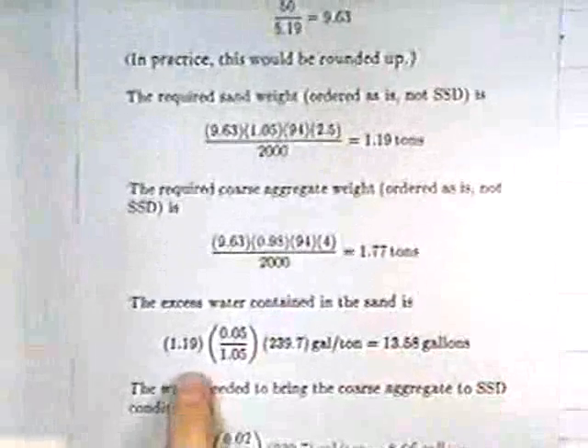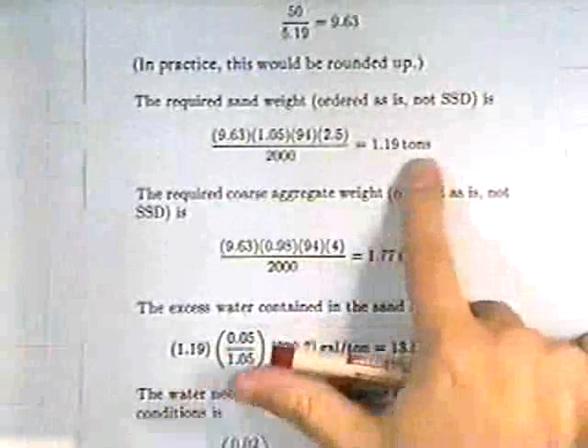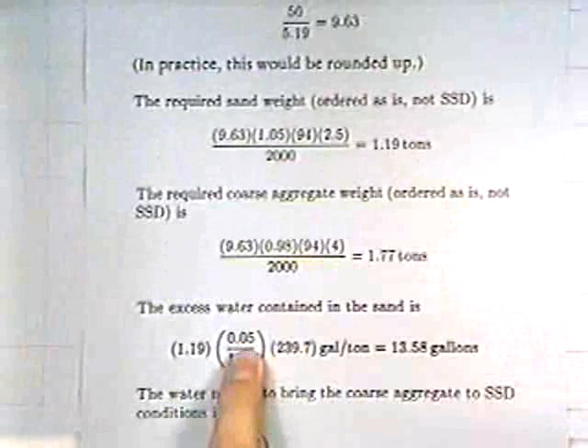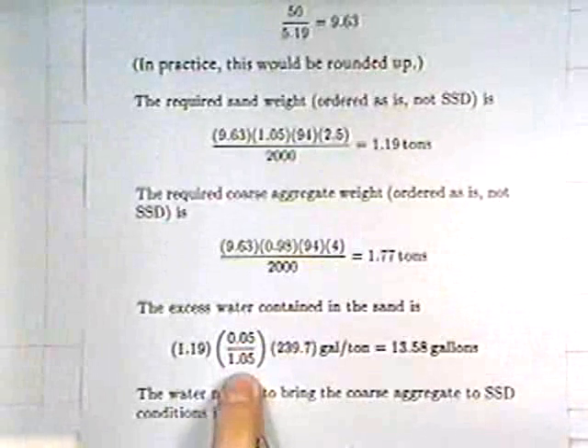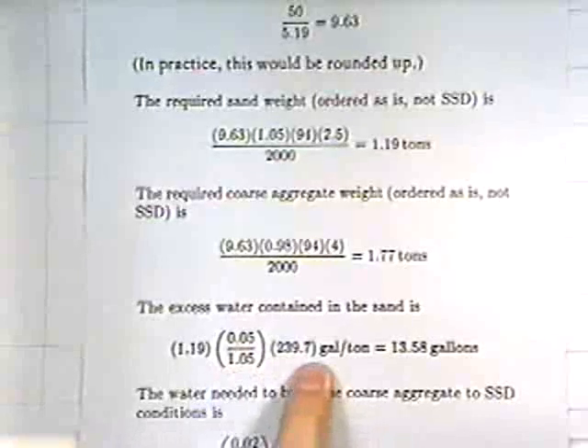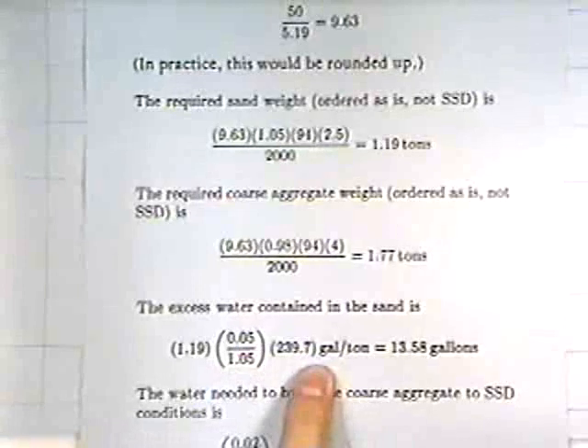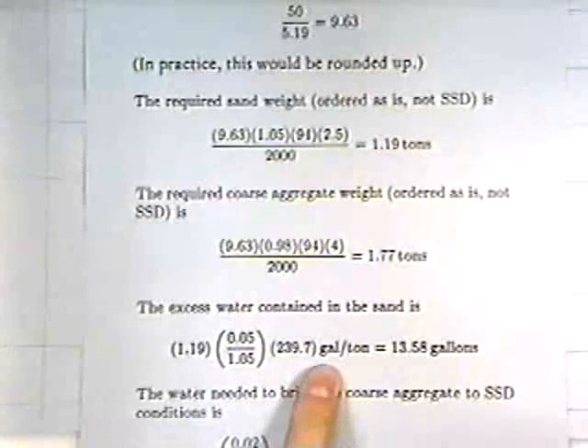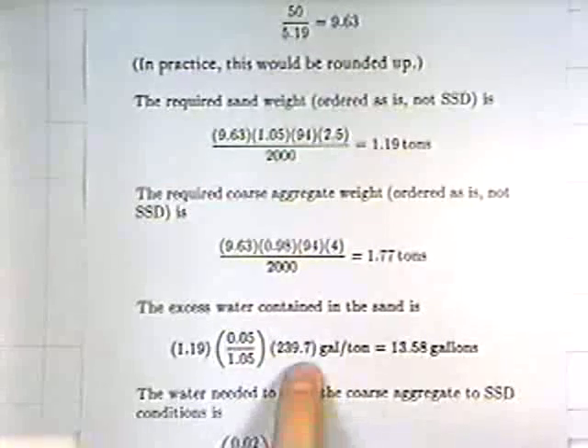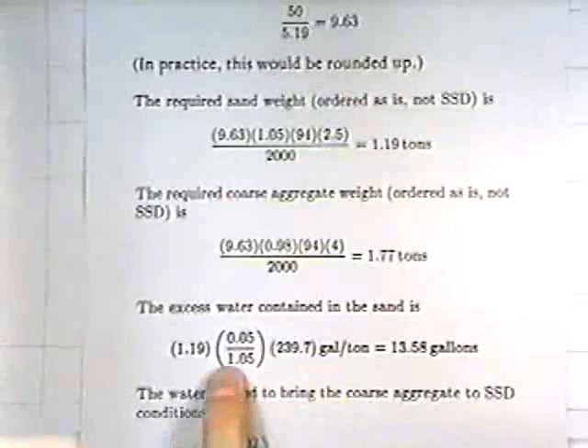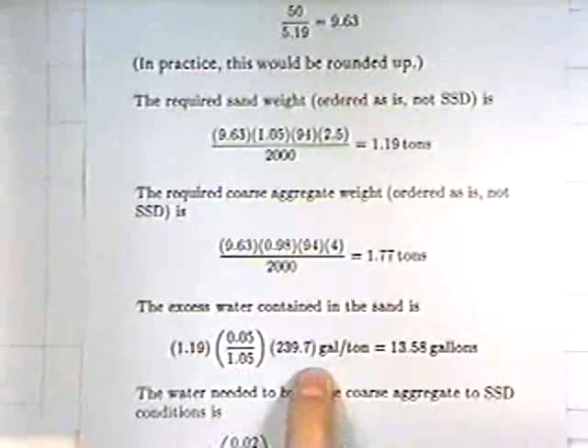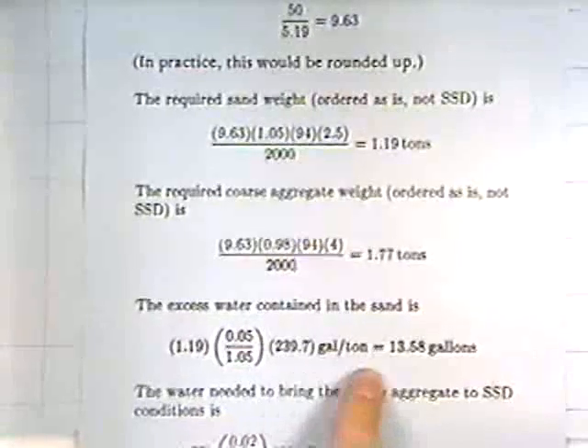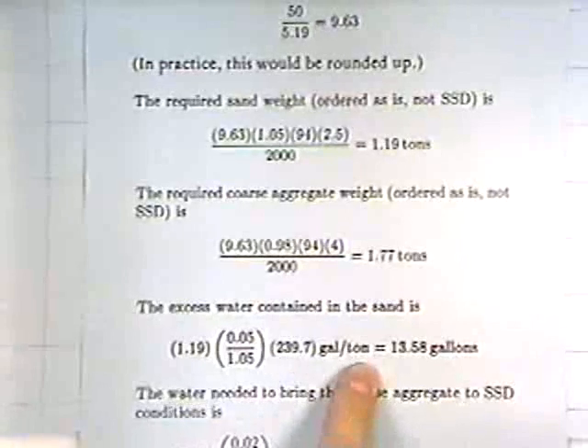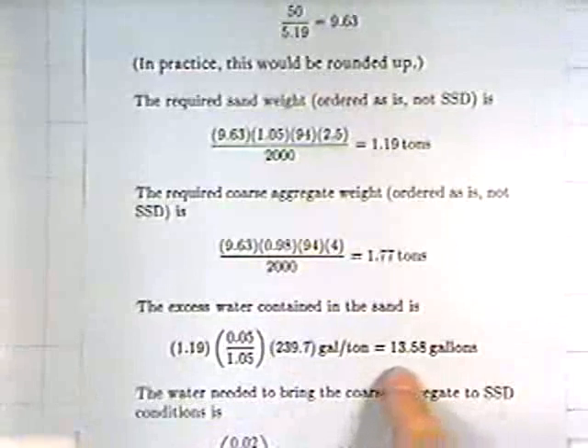The excess water in the sand you can calculate from this formula. It's the 1.19 tons from up here. That's the amount of sand that you're using. You have a 5% excess, divided by your 1.05, that's basically just like a ratio. It's the amount of water as compared to the amount of sand, times your 239.7. And I'm trying to think of where that comes from. That's gallons per ton. How many gallons per ton of water? The ratio, 2.3. 239.7 is a constant. Okay, that's probably the weight per ton, right? So it's the amount of volume per unit of weight. Okay, that could be. All right, and that turns out to be your 13.58 gallons.